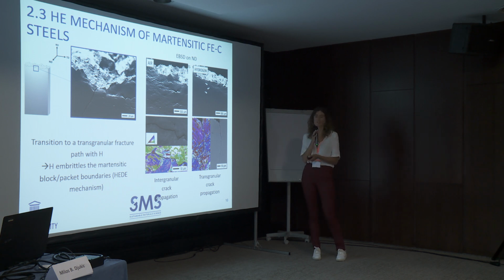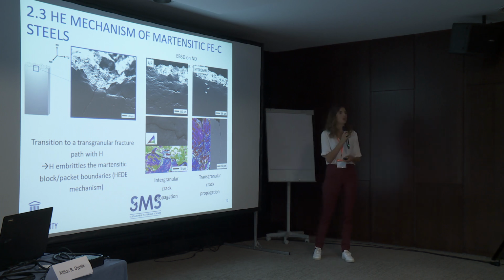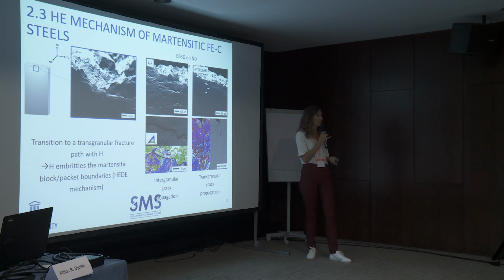And thus, the resulting cleavage type of fracture really originates from the HEDE mechanism. So we have decohesion of our martensitic blocks and packet boundaries. So what can we conclude? Well, the martensitic blocks and packets are really the weakest link in martensitic structures.